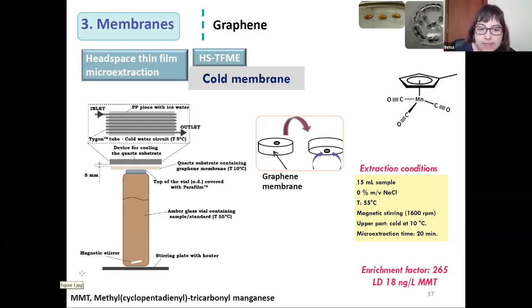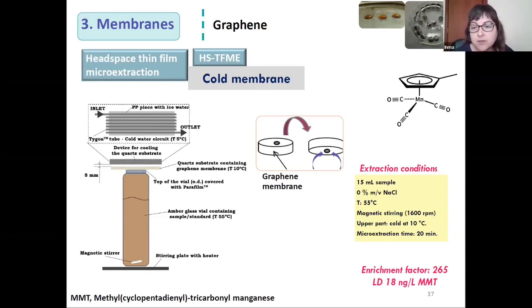Here, while stirring and warming, we were able to extract the MMT from the aqueous solution to the headspace, and then it was retained in the graphene membranes. However, the extraction efficiency can be improved by placing this laboratory-made system to cool the membrane in the upper part. It allows us to obtain an enrichment factor of around 265 in the case of these organometallic compounds. In this case, the interaction is due to the cyclopentadienyl pi interaction with the graphene membranes.